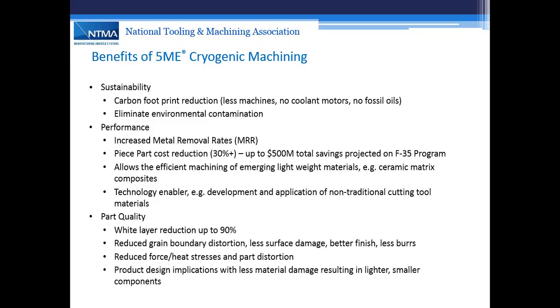Part quality: there's a significant reduction in white layer. The white layer is that untempered martensitic layer that happens after you machine a component in either steels or titaniums. It basically remelts and recrystallizes on the surface of the material. It's martensitic, very, very brittle. And being very brittle, sitting on a tougher material, as the material flexes, the crack will propagate in the extremely brittle skin and then propagate through the tougher material. So it's extremely important, especially in aerostructure and aero engine components, that it is absolutely minimized.